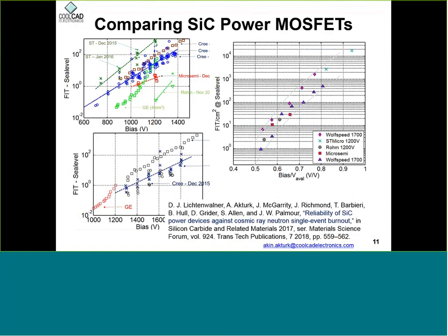So this is a very busy picture, but the main takeaway point here is that we regularly test devices, silicon carbide devices or gallium nitride devices or silicon devices. We mostly test the silicon carbide devices. And then we get these failure in time curves and use them in reliability analysis, so that the circuit designers can use them to design more resilient, terrestrial neutron resilient or terrestrial radiation resilient circuits, so they would not fail due to this effect.